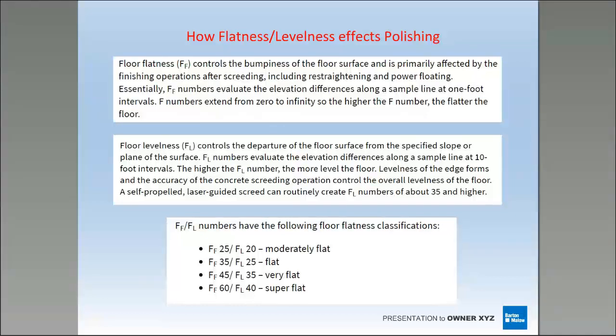Don't have to shoot for the moon, because if you tell the guy you want an FF50, think about what he has to do to get there. Does he have to get a bump cutter? Does he have to do anything that's going to adversely affect you and your polish that you may not want him to do? Can you live with a 45 or a 35? Make it a little easier on him, make it a little easier on you, right?